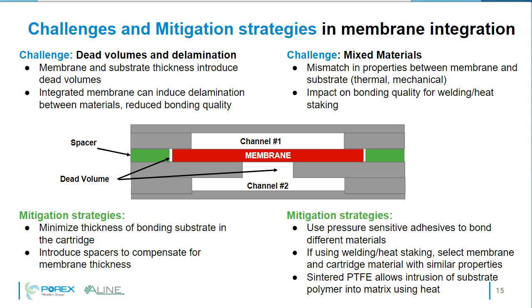And this is where having a larger variety of options on the membrane materials really comes in handy, and so having a large catalog of membranes is really important here. An alternative here is the use of sintered PTFE that allows intrusion of the substrate polymer into the matrix using heat. You're basically creating an intimate contact between the similar materials to really create a good bond between them.